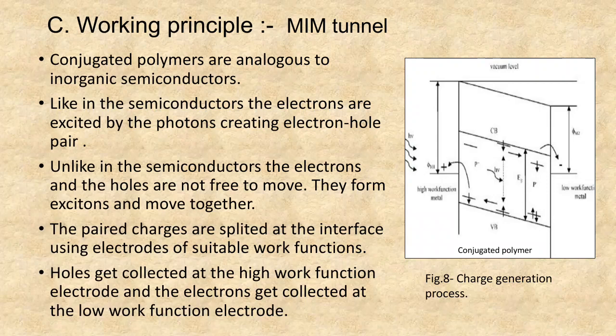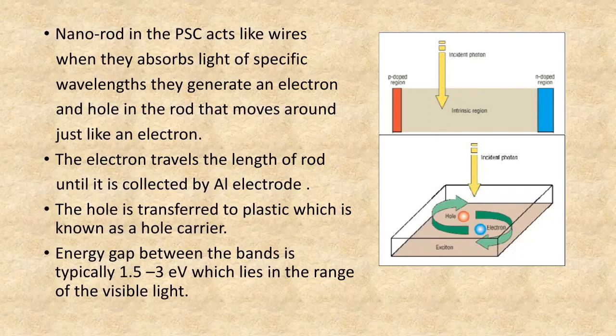Like in the semiconductor, the electrons are excited by the photons, creating an electron and hole pair. But unlike the semiconductor, the electrons and holes are not free to move. They form an exciton and move together. The paired charges are split at the interface using electrodes of suitable work function. The holes are collected at the high work function electrode, whereas the electrons get collected at the lower work function electrode. The electron travels the length of the rod until it is collected by the aluminum electrode at the end, and the hole is transferred to the plastic, which is known as the hole carrier.